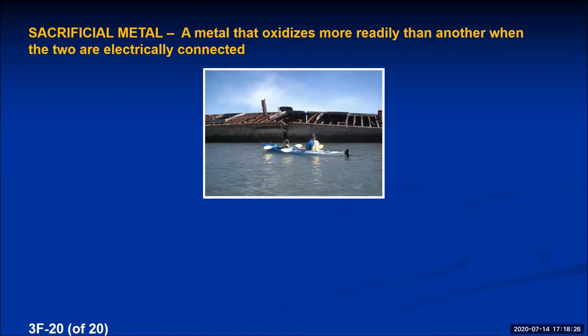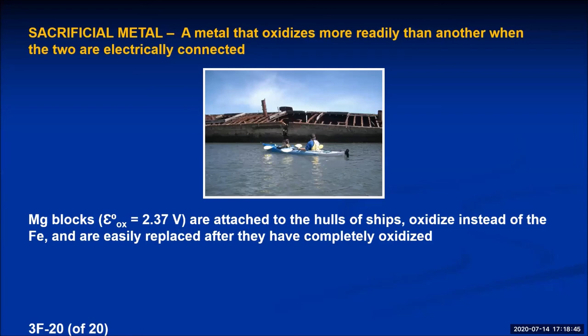Most ships that sail in the ocean are made of iron. And iron oxidizes really readily. And you don't want giant billion-dollar ships to oxidize away and turn into something like this. So what people do when they produce large ships is they actually attach to the hulls of those ships magnesium blocks. Look at the oxidation potential of magnesium, 2.37 volts, really high, very spontaneous. So these magnesium blocks are attached to the hulls of ships. And because magnesium is more reactive than iron, they oxidize instead of the iron, and they're more easily replaced after